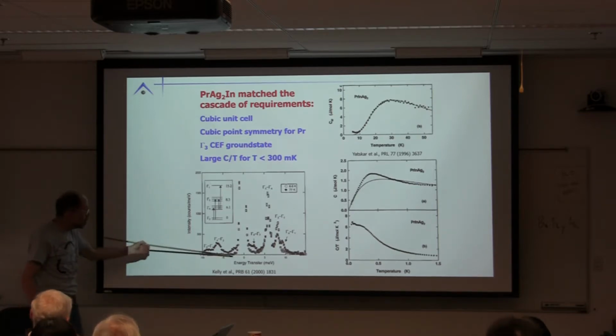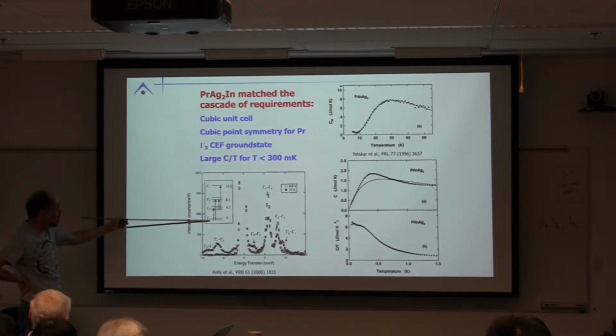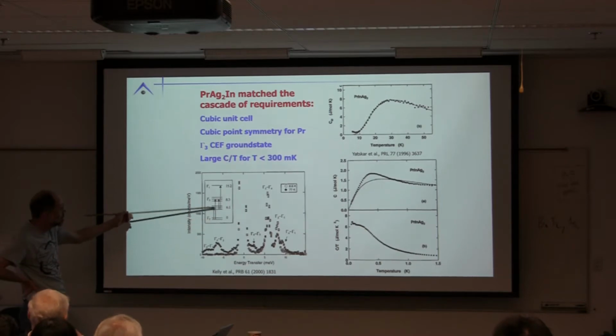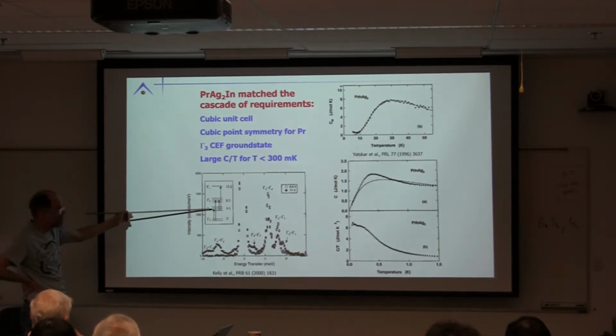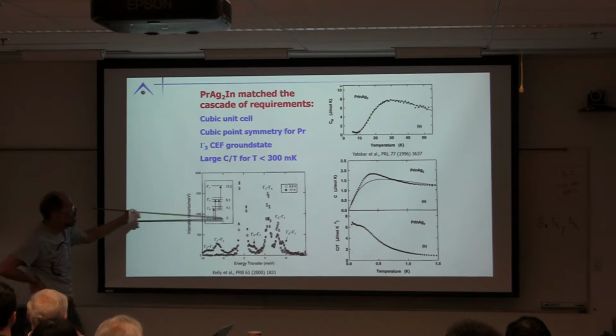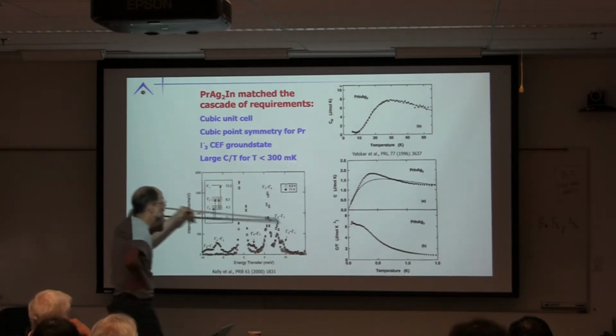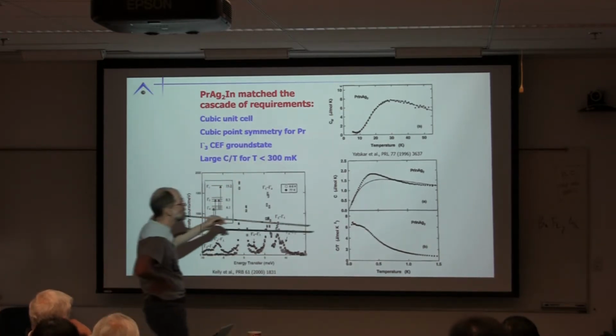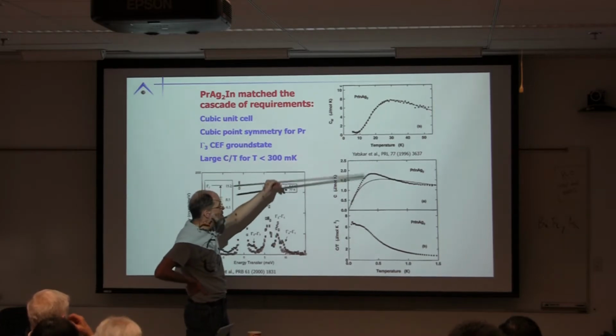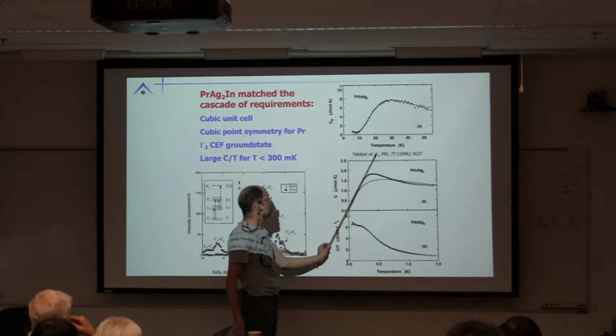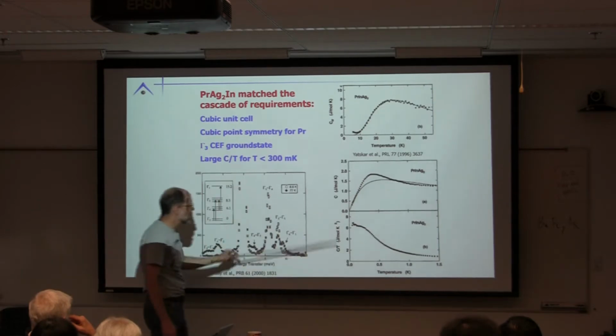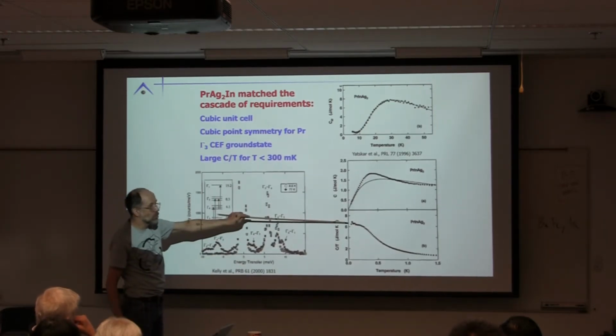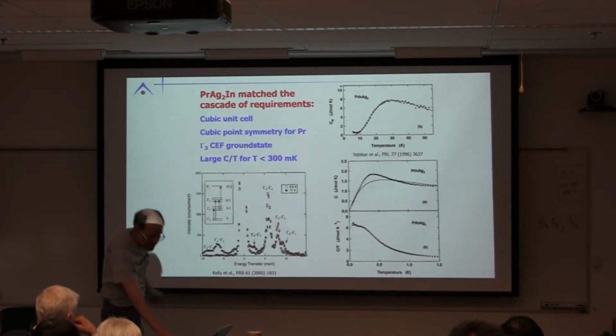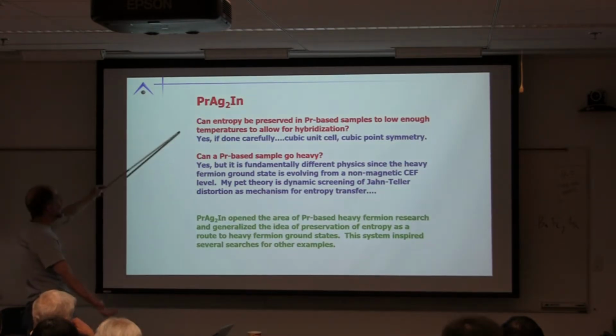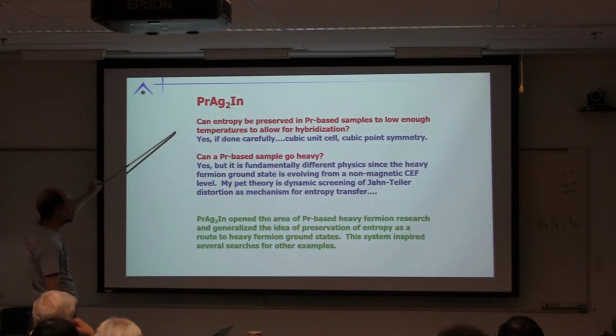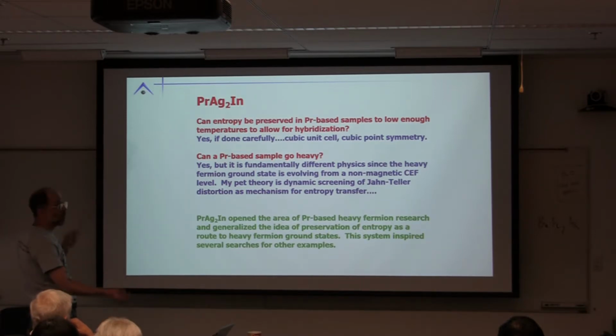We were able to reproduce their CF splitting, both from inelastic neutron scattering, gamma-3 separated by 6 meV, so about 60 Kelvin from the highest state. We can measure specific heat, fit it to this distribution of Schottkys, but at low temperature something's happening, and if we look at low temperature, we have a linear specific heat going through zero. Plot C over T, and you have over 6 joules per mole K squared. So, can entropy be preserved in Pr systems to low enough temperatures to allow for hybridization?